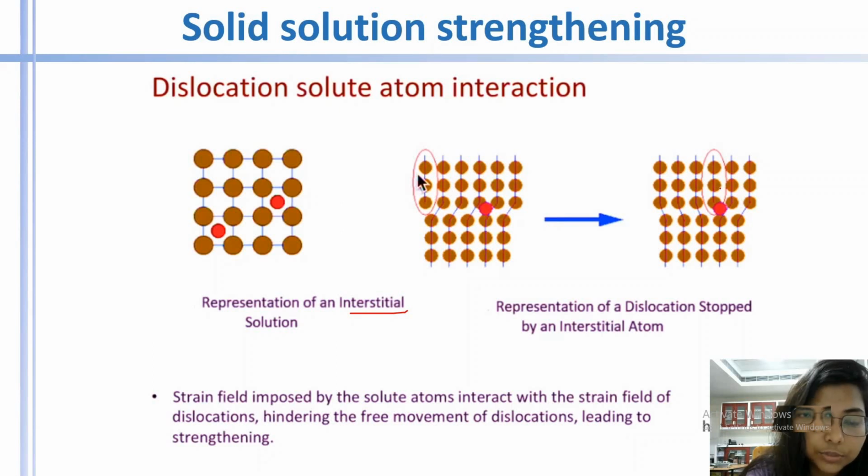The strain field imposed by the solute atoms interacts with the strain field of the dislocations, hindering the free movement of the dislocations, and this leads to strengthening.